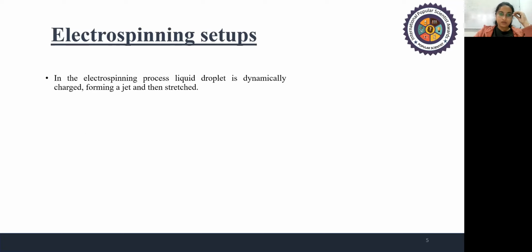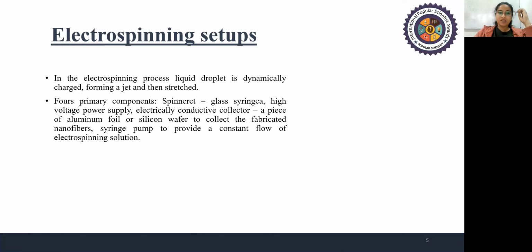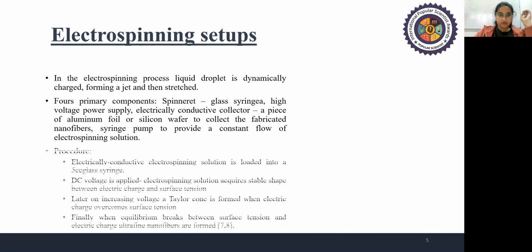So here, I am explaining the electrospinning setup. In the electrospinning process, there is a liquid droplet which is dynamically charged, forming a jet that is then stretched around. There are four primary components for electrospinning: a spinneret, which is a glass syringe, a high voltage power supply, and an electrically conductive collector, which is a piece of aluminum foil or silicon wafer to collect the fabricated nanofiber. There is a syringe pump which provides the constant flow of spinning solution.